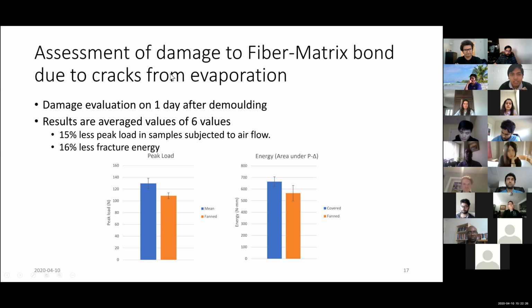So this is the assessment of damage due to cracks from evaporation. After 1 day of demolding, I leave them for one more day under exposure to a constant flow of air. And then these are basically 6 samples tested each. I compared the peak load and the energy under the curve. So in both the cases, I observed that the samples which were under a constant flow of air had less of a peak load. So the bond was weaker, as well as they had less fracture energy inside.